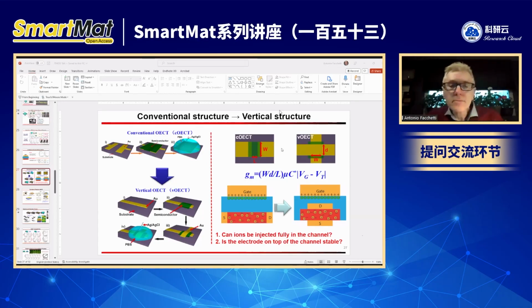Yes, most of them have sulfur, and the major reason is that sulfur is a soft atom. It means that the electron cloud really likes to diffuse, and this diffusivity of the cloud helps the pi conjugation of the core of the aromatic ring, and also helps the stacking when the molecules stack, to have a very high electronic coupling.